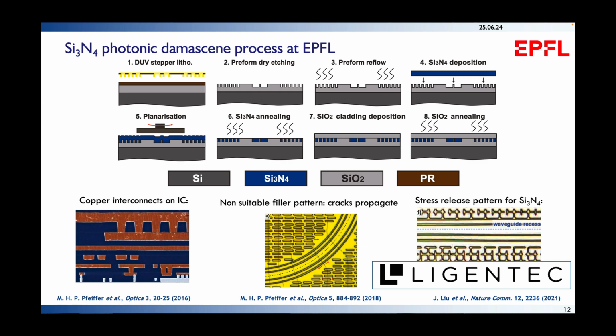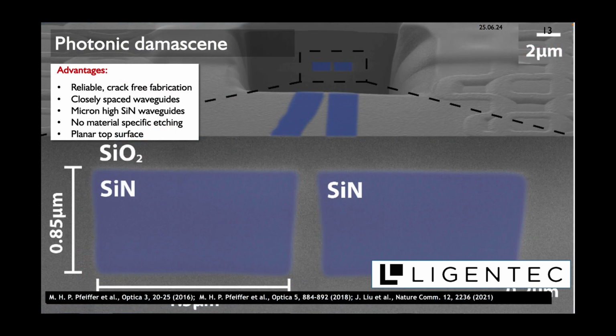Now, how low does the loss go with these structures? The loss we can get with these structures is about 10 dB per meter. So very significant advance over silicon, but still not really at the level of where we would like to be. Now, a few things about this Damascene process. For the experts, it's a crack-free, reliable fabrication, wafer scale, very high waveguides, even micron scale is possible, and we have a top planar surface that we can also use to transfer other materials like ferroelectrics.